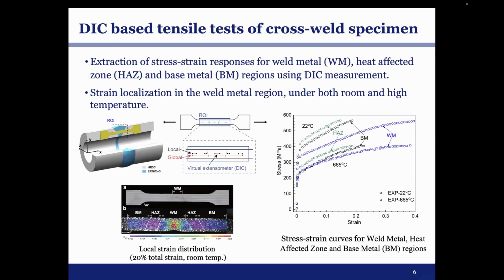To begin with, we conduct some experiments. So we machine such cross-weld specimens from the welded tubes, and we perform tensile tests at different temperatures with DIC measurements. From the tensile tests, we can extract stress strain curves, not only for the whole specimen, but also for different regions. That is the weld metal region, heat affected zone region, and base metal region. And also we have the full field strain measurements. We can see that for this specimen after the tensile test, there is a strong strain localization in the middle part. That is the weld metal region.